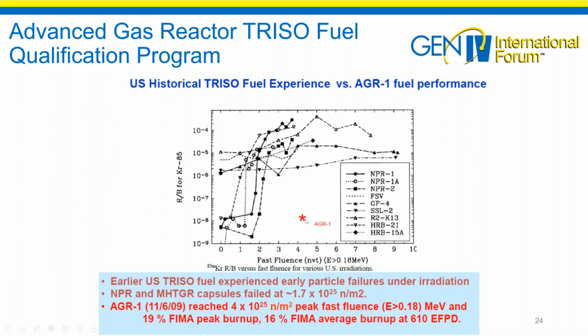Again, I pointed to this in our earlier slide. Here's where the AGR-1 average is, and here's where our burnup is. Earlier fuel experience wasn't too great, and we had failures early on, but we reached a high fast fluence. That's a measure of the way we measure displacements per atom or damage in the particles at 19% FIMA, and our average was 16%, and we had 610 effective full power days.